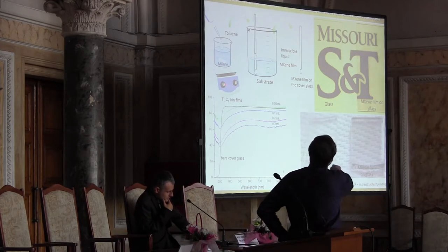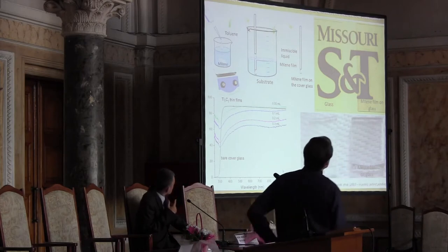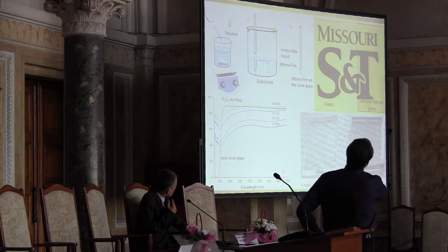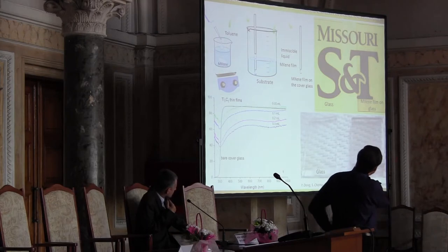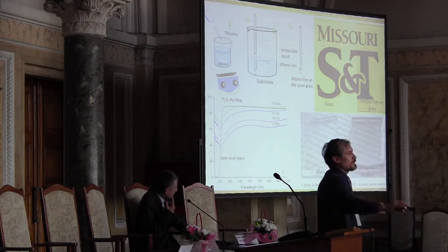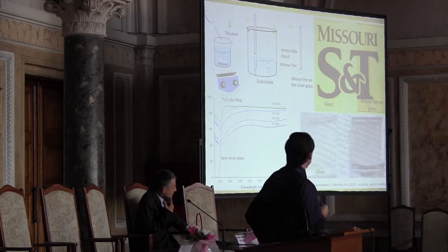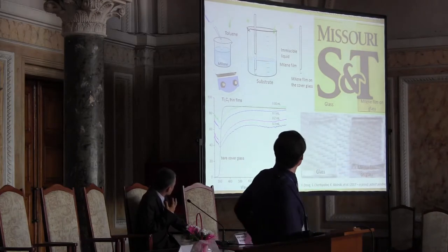You can use it pretty much in any way and produce very thin films. So this is basically the schematic of how we do it. We put the substrate in the aqueous phase, form the film at the interface, then raise the substrate, it goes through the interface and picks up the film. So we have now one slide here, this interfacial film. And this is how it looks. You can see this is pure glass, this is glass with MXene film. You cannot see much, first of all, because this film is thin. Because the projector doesn't show the colors, but believe me, there is a film. I also show you another photograph, and here in the corner, you will see the white and bright triangle. That is the spot which I used to hold the glass. So the dark area here is covered with MXene film. Remember, using the spectra of these films, we see plasmon resonance here around 700 to 800, something like that.